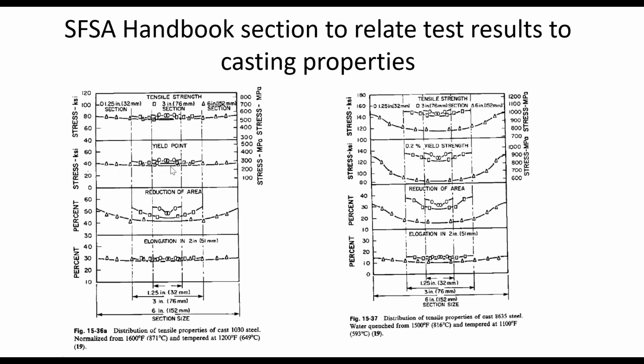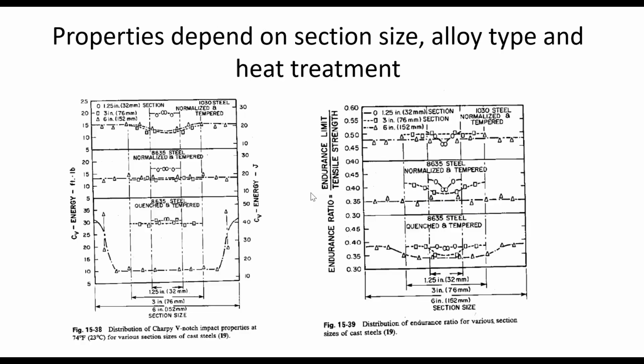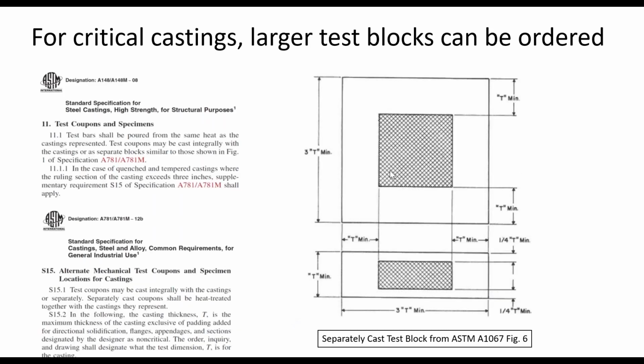So in carbon steel in the center of the 6-inch section, I'm a little under 40 KSI. In 8600, I'm still over 80 KSI. So those alloyed steels still give me improved properties even when the heat treatment can't reach into the center. And of course, today you're not only concerned with strength, but also toughness. And so we have some information about the variation of toughness with section size and fatigue properties.